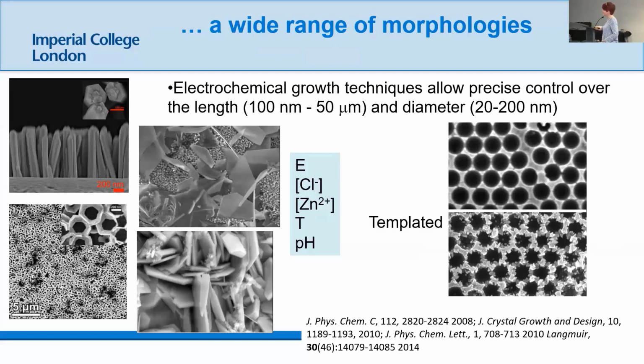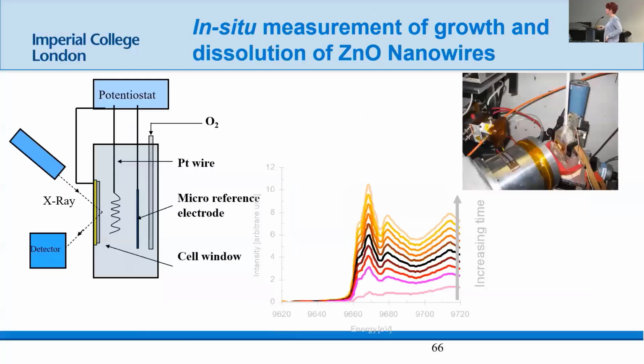And the parameter space includes this range of parameters: pH, temperature, the concentration of zinc 2+, the concentration of chloride, which has a huge effect, and I'll explain why in a minute, and the electrochemical potential, which is driving that oxygen reduction. So we were interested in really understanding the role of each of these parameters, how this process worked, and whether you could find a design map that would help you pick a set of conditions to make the material that you wanted.